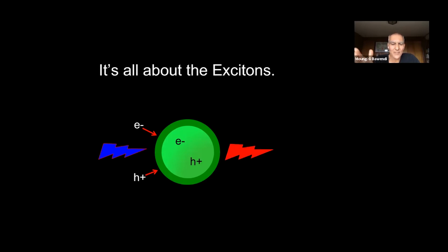When the exciton is done living and it's interacting with the photon field around it, then it emits light, which is redshifted from the light that you're exciting with, and that's the basis for the applications that are commercial today. You can also get the electron and hole out from their confined state, and if you have light in and then electrons and holes out, that's the basis for making a photodetector or a solar cell.